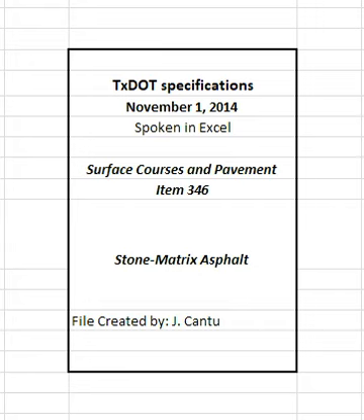4.5.1 Storage and heating of materials. Do not heat the asphalt binder above the temperatures specified in Item 300, Asphalts, oils, and emulsions, or outside the manufacturer's recommended values. Provide the engineer with daily records of asphalt binder and hot mix asphalt discharge temperatures, in legible and discernible increments, in accordance with Item 320, Equipment for asphalt concrete pavement, unless otherwise directed. Do not store mixture for a period long enough to affect the quality of the mixture, nor in any case longer than 12 HR unless otherwise approved.